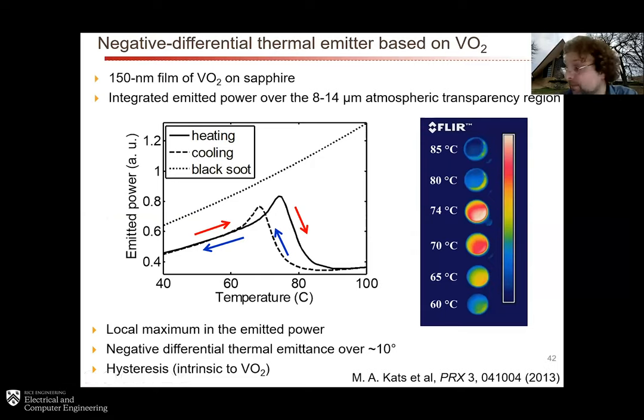Actually, a few years ago, we published a paper in collaboration with and led by Evelyn Wang's group at MIT, and they essentially put these samples into a chamber suspended on very, very thin legs so that you can thermally isolate it in terms of conductivity from the walls. You then pump in a fixed amount of energy, and you see what happens to the temperature, and you can get really interesting phenomena. Like, you essentially get a runaway.